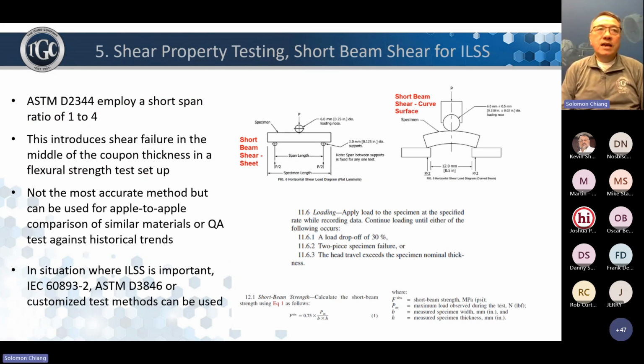And ILSS can be obtained using the ASTM method plus the IEC method, and they use or even customized test methods, but most of them require special fixtures. And there's also a quick way to do ILSS. It's essentially a 3-point flex test, but then you reduce your span distance to something like 4:1, and you essentially force the coupon to fail in the ILSS manner. So it's a quick way.